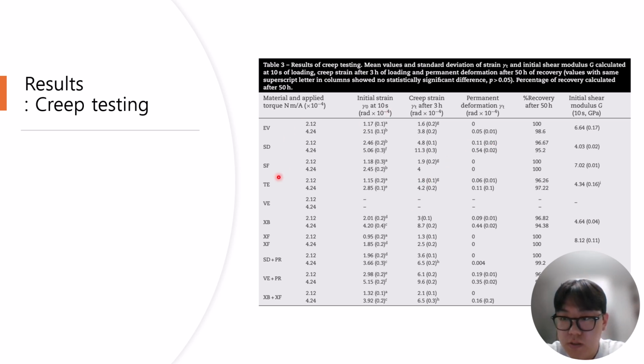This table shows the elastic recovery of each material after removing the torque and letting it rest for 50 hours. Restorative types like SF and XF recovered almost completely, showing values close to 100%. That means they returned to their original shape after the load was removed, a good sign for long-term durability.